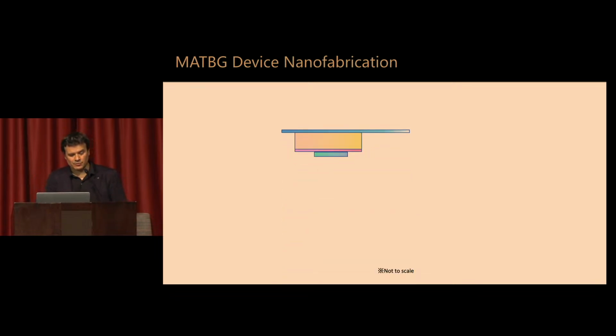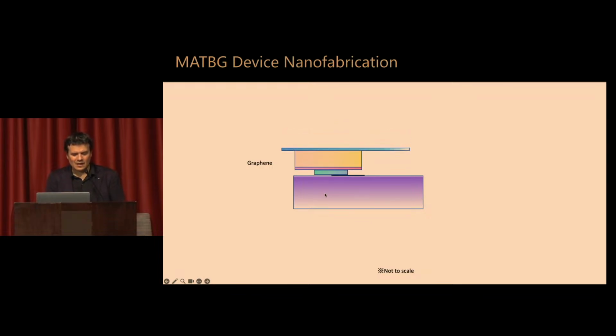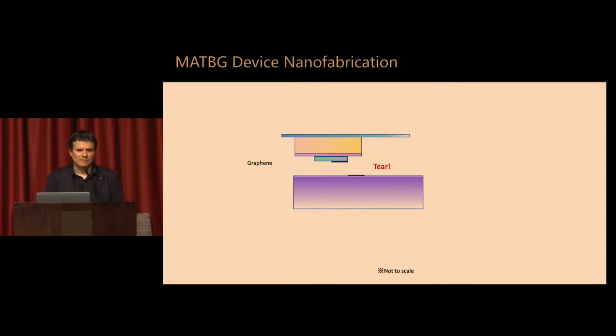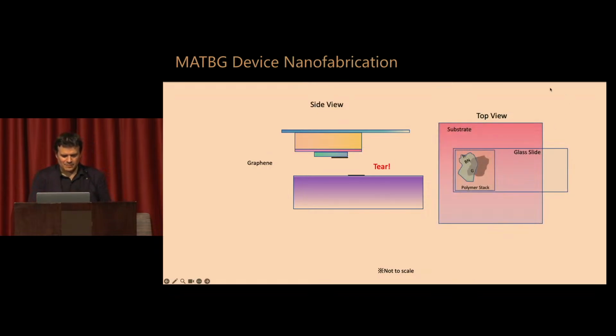Then I bring another substrate where I have graphene on it. As I showed you before, we do this with Scotch tape. Still to this day, we do it with Scotch tape, okay? And what I can do is position my hexagonal boron nitride flake on top and in the middle of the graphene sheet, so that now I come down and I tear half of the graphene. So from the top, this looks like I have my silicon substrate with half of the graphene, and I have my glass slide with my polymer, with my hBN, and the other half of the graphene on it.